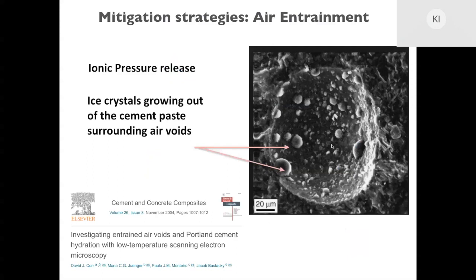So the usual technique to prevent freeze-thaw is air entrainment agents. In this way, small bubbles are introduced in the concrete, and what they really do, you can see here on this electron microscopy picture, is they create space inside the cement where ice can grow, and also this ionic pressure can be released. So basically, in a way, they are postponing the saturation point, and like this, the damage is taking longer to occur.